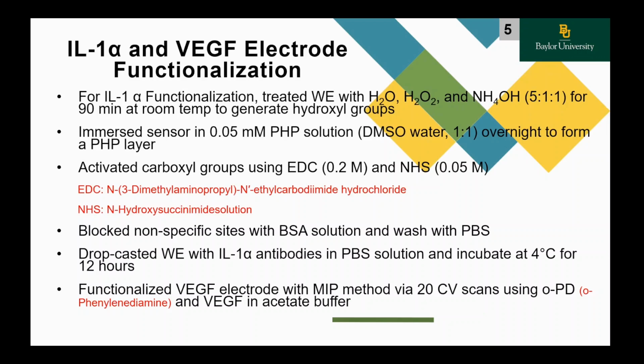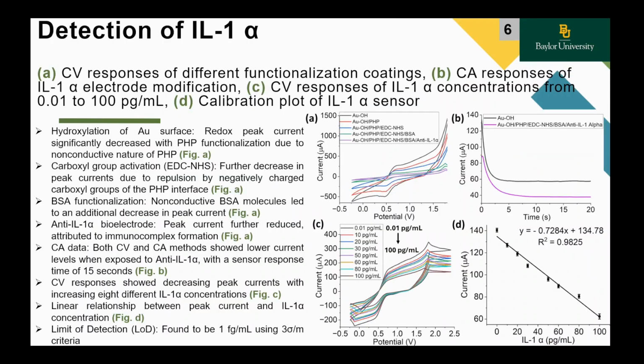The VEGF electrode was functionalized with molecularly imprinted polymer, MIP, coupling method using OPD, and VEGF solution in acetate buffer, and tested with VEGF electrode, VEGF urine sample. So here are the electrochemical measurements for interleukin-1 alpha electrode.